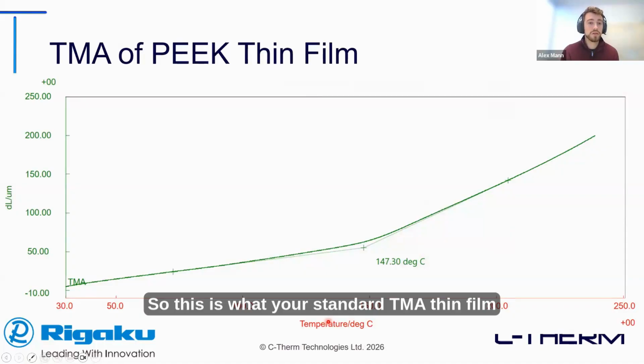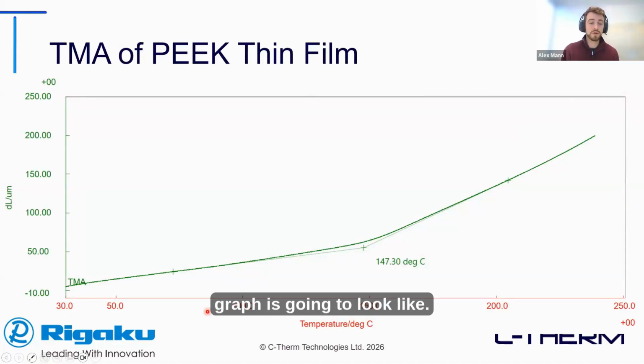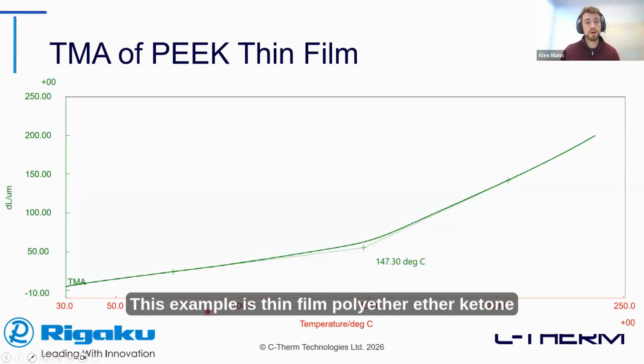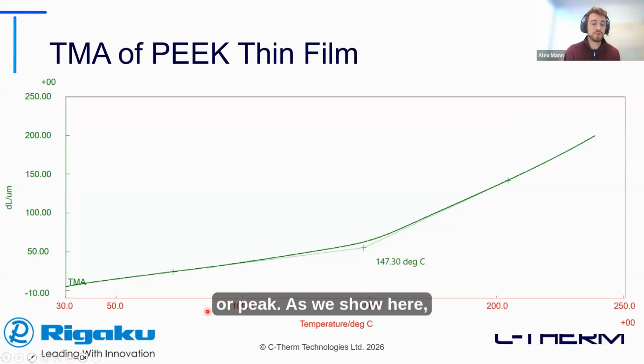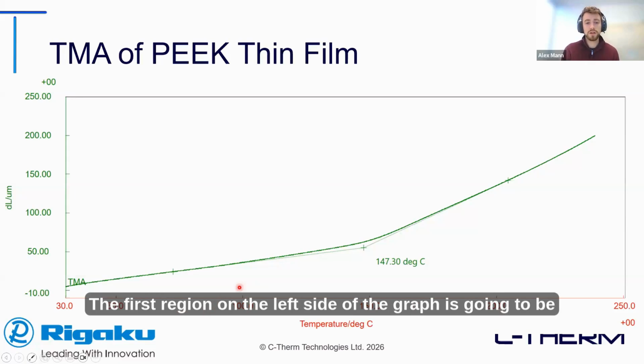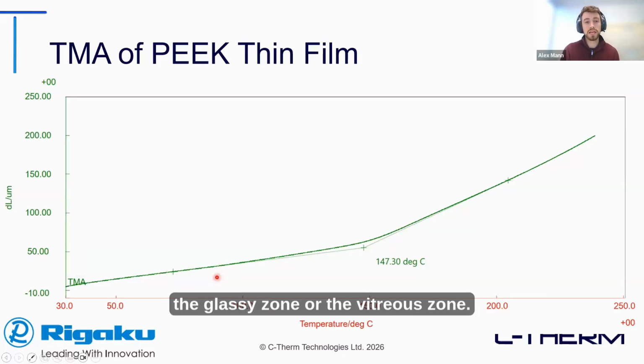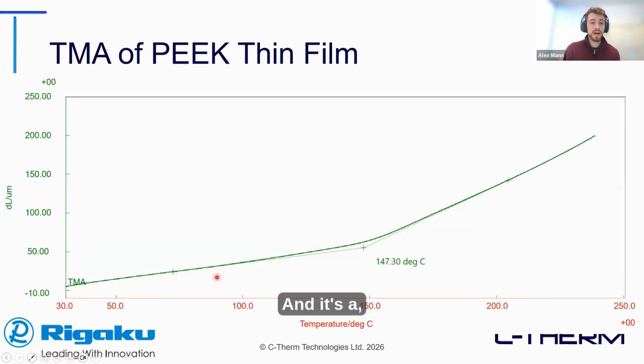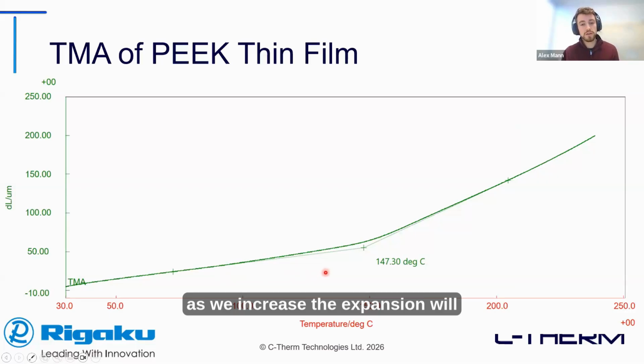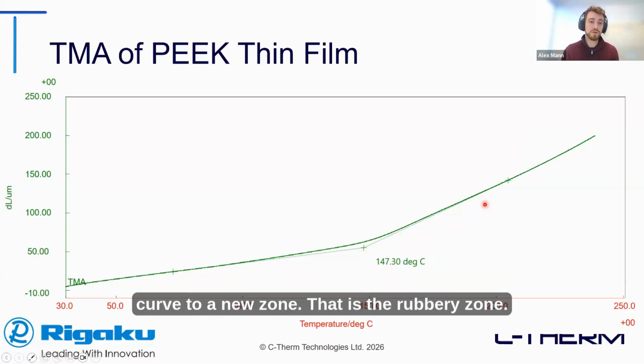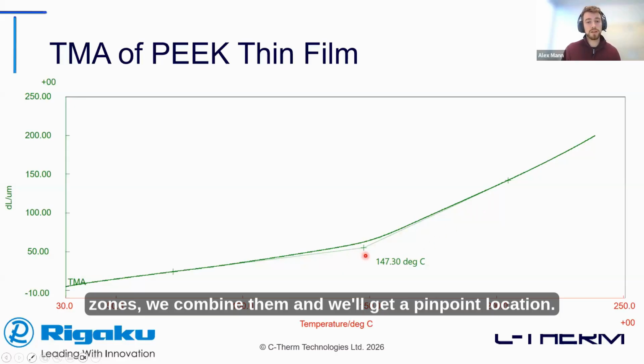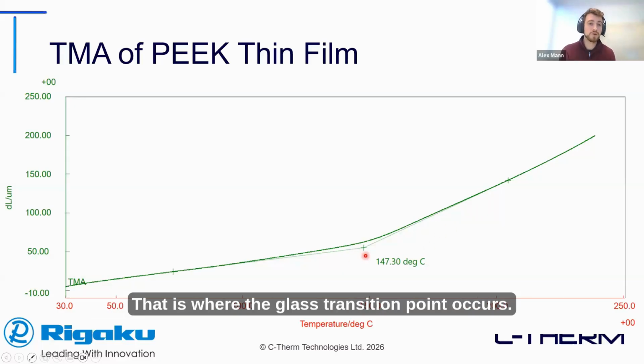This is what your standard TMA thin film graph is going to look like. This example is thin film polyether ether ketone, or PEEK. We see there are two primary regions. The first region on the left side of the graph is the glassy zone, or the vitreous zone. As we increase, the expansion will curve to a new zone. That is the rubbery zone. If we take the tangent of each of these zones and combine them, we get a pinpoint location. That is where the glass transition point occurs.